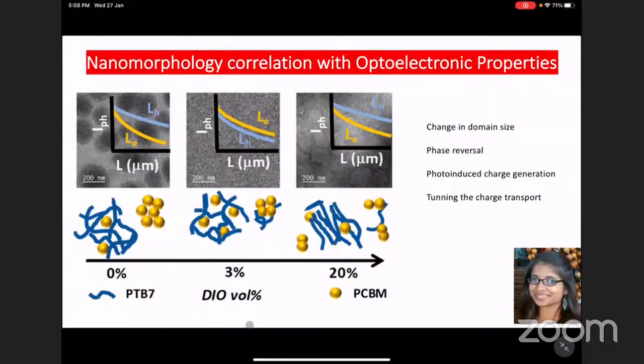Further, in order to understand this nanomorphology and correlate it with the optoelectronic properties, we deliberately used lots of different percentages of DIO, not only the optimal 3%. We went from 0% all the way to 20%, and that work was done in collaboration with Achanta Venugopal to understand all these charge transport length scales. Optical simulations were done by Achanta's group. And we could see that when we go from 0% to 20%, we see a change in the domain size.